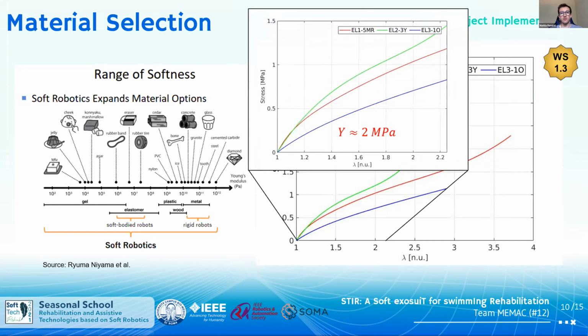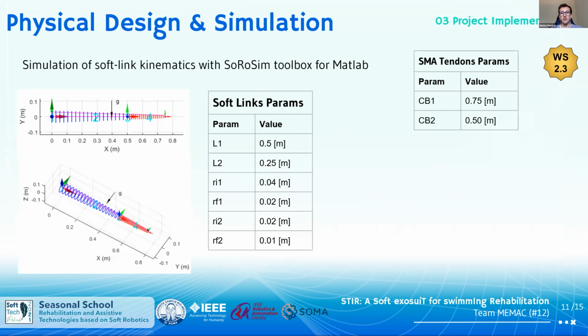Here we can zoom on the results and we can see that the first elastomer and the five-term Mooney-Rivlin model provide a Young's modulus of around 2 megapascals in this region, which confirms that the results of the simulation are compatible with the data shown for elastomers. Then we have used the results of the first workshop with the Sorosim toolbox to simulate the kinematics of the soft link. Here you can see in the slide both the parameters as well as some pictures